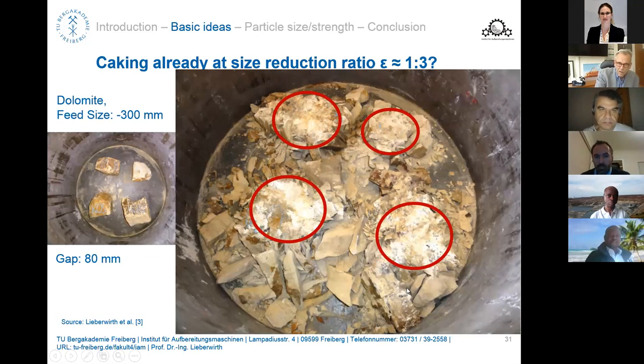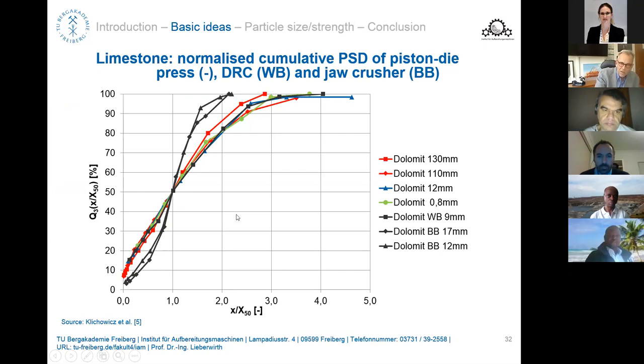So this is another picture here. The diameter of the pot is about 1 meter in this case. You see the original particles here, in this case dolomite, with a gap of 80 millimeters, and you could see the larger lumps falling aside, of course, but inside you always had the formation of this caking and this particle bed. We did some comparable tests with dolomite with different feed sizes, and different presses actually, also 130 millimeters, 12 millimeters, and 0.8 millimeters. That was all piston die tests here. And we compared the results with the double roll crusher test and with the jaw crusher test at different feed particle sizes also.